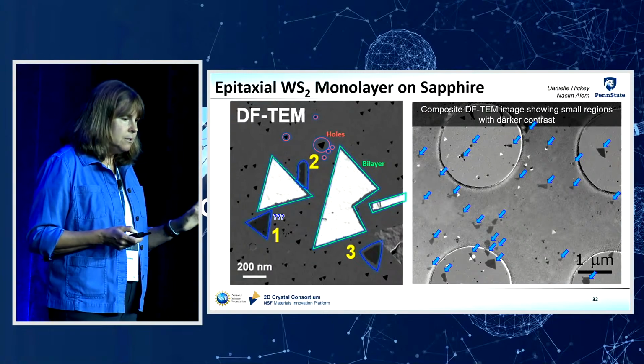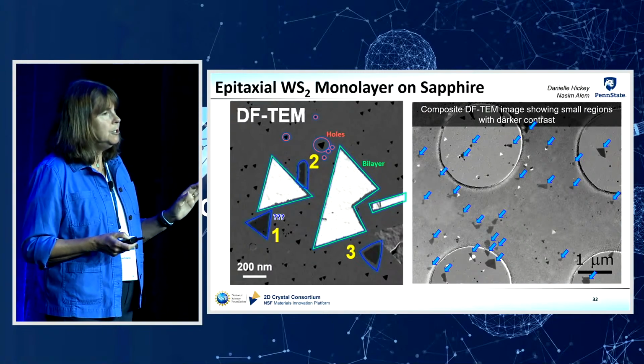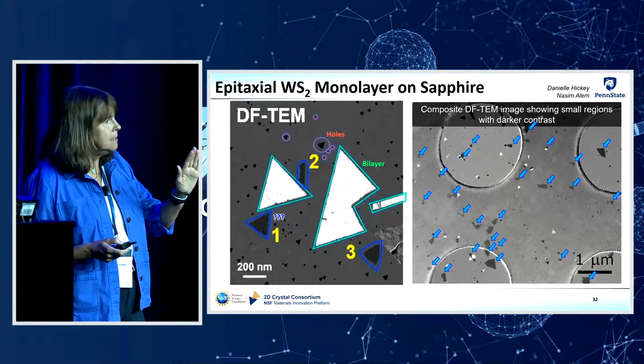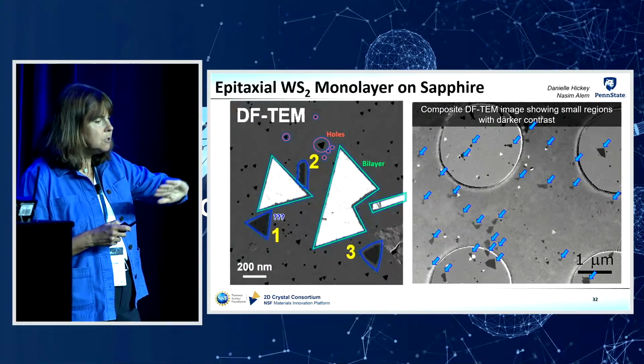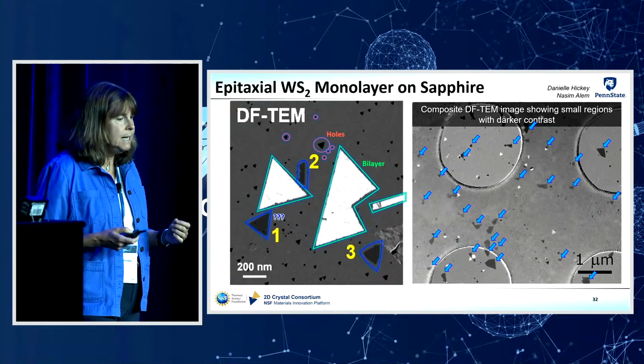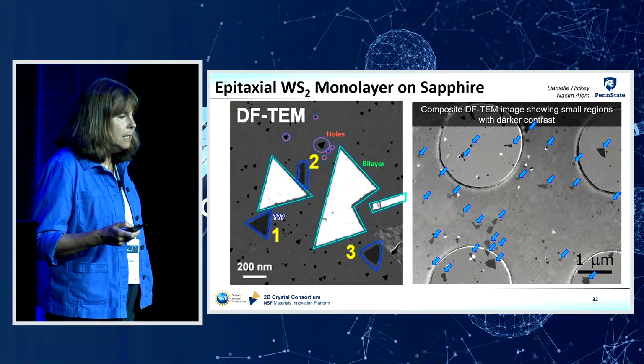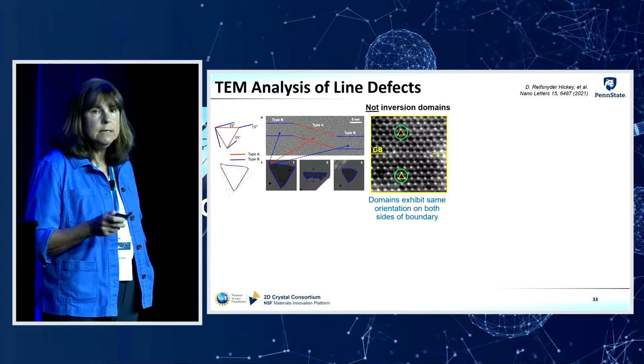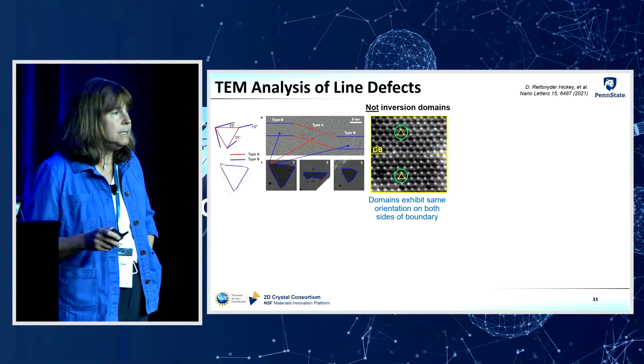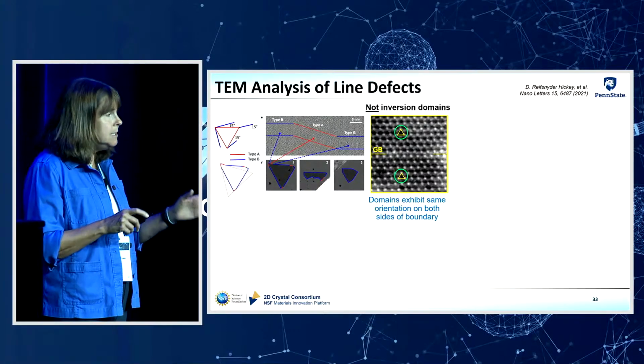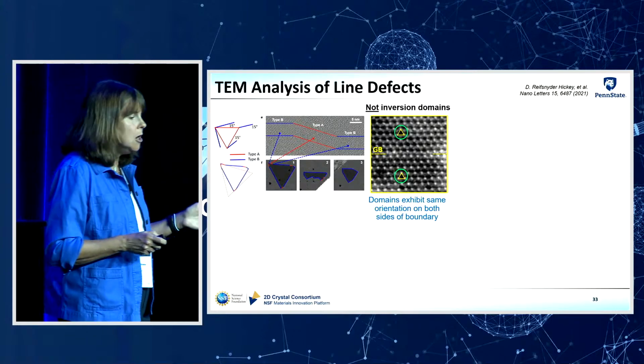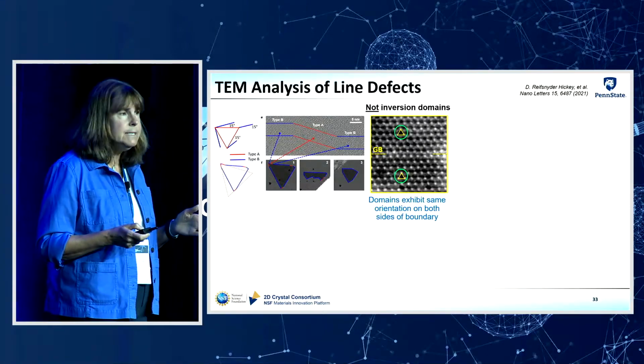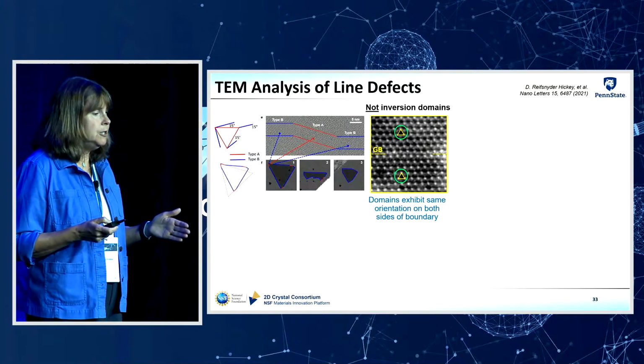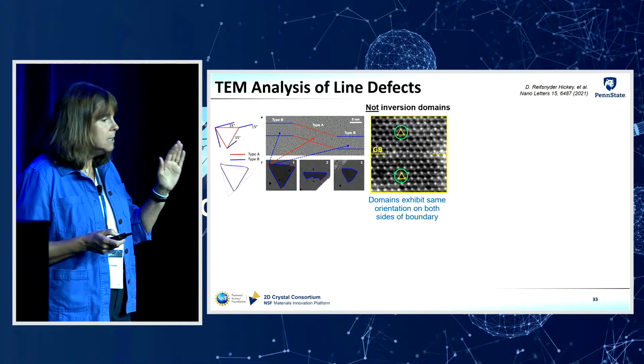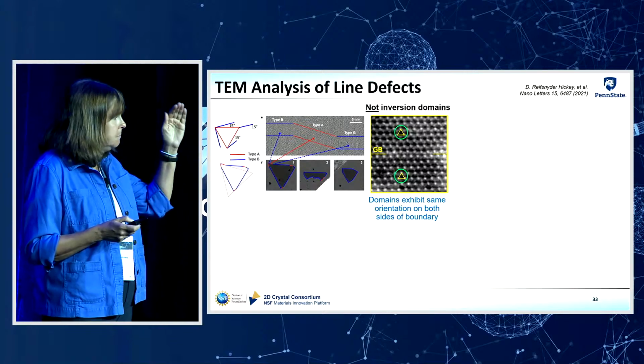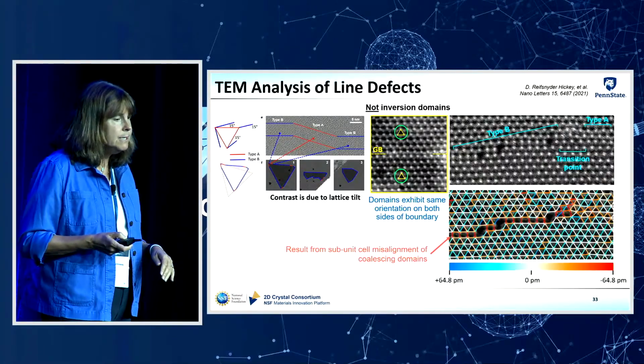Now, when we initially saw this, we thought, oh, these are inversion domains, right? Because we still have some of our domains that are misoriented, right? So we expected to have some inversion domains present in our films. But our colleagues did some very detailed TEM analysis of the grain boundaries associated with these features that have a darker contrast. And what they found is that these are actually not inversion domains. The orientation of the tungsten disulfide is the same on both sides of one of these grain boundaries.